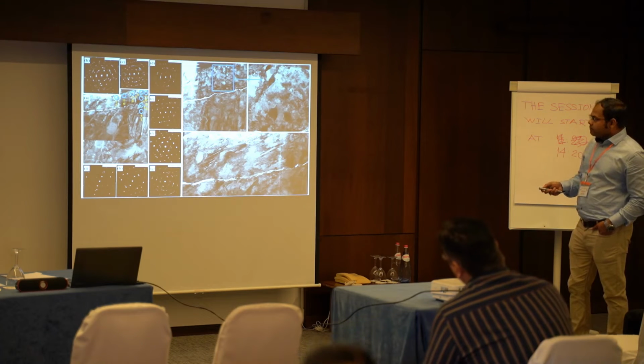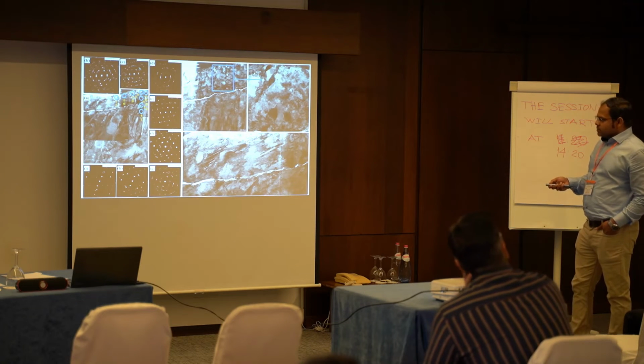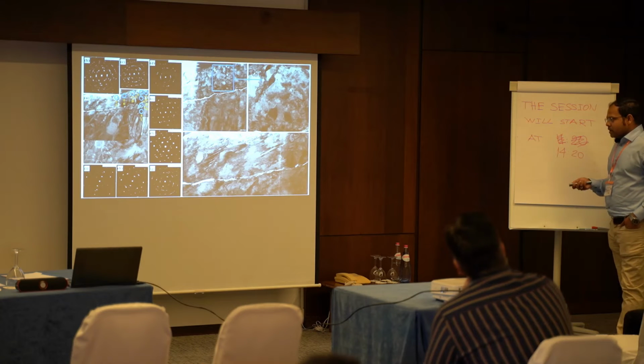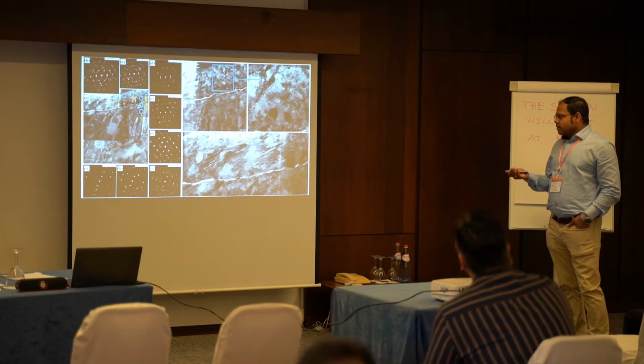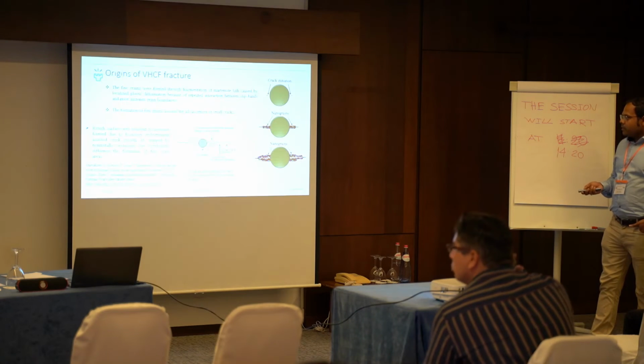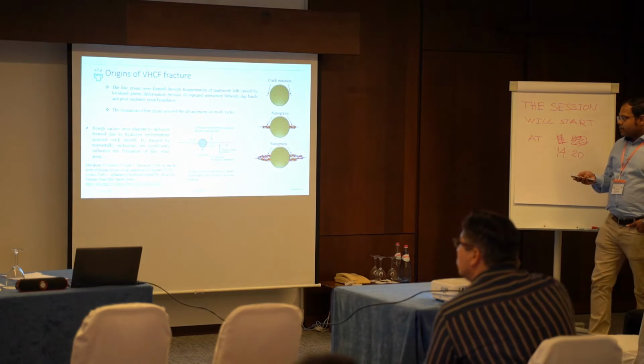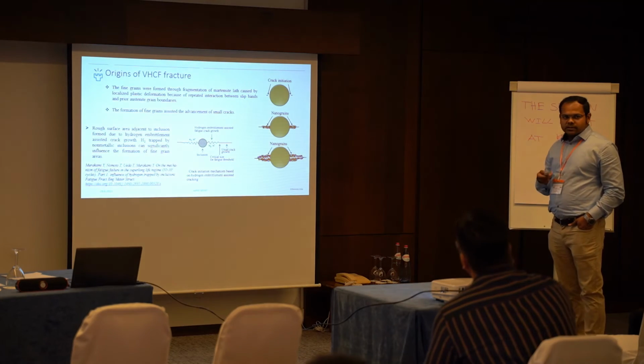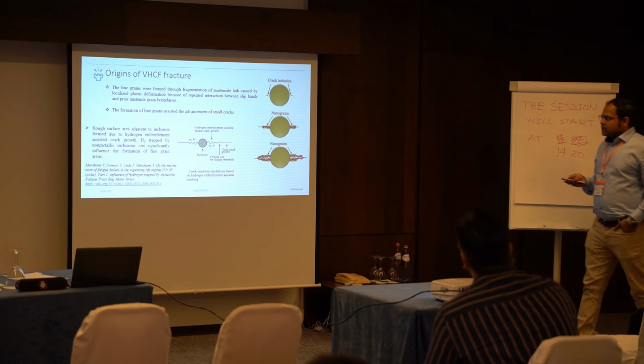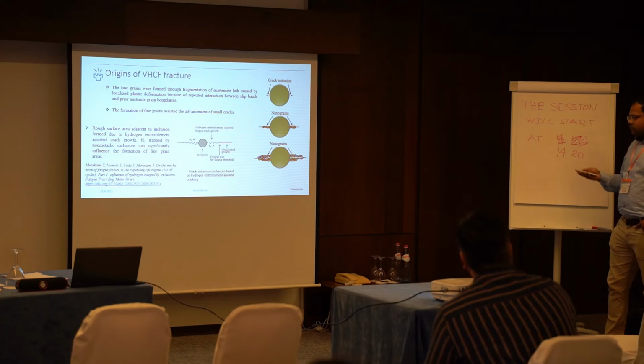And then you can see that beyond this region, no such granular area exists. So it's only twin martensite present. This is not surprising, because twinned martensite is generally observed in medium carbon steel, and twinning occurs in order to accommodate the plastic strain. As I think Professor Chai also discussed in this modeling, it's still quite confusing because a lot of people assume different phenomena.